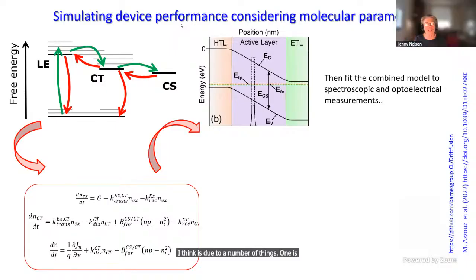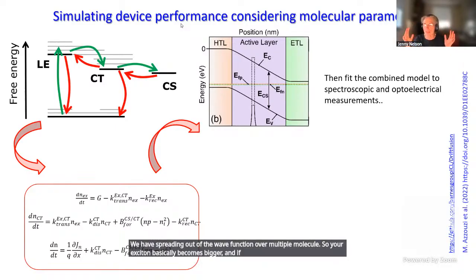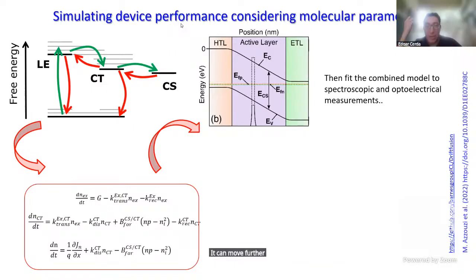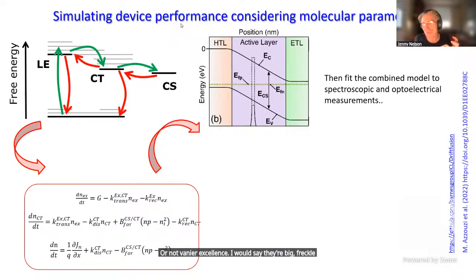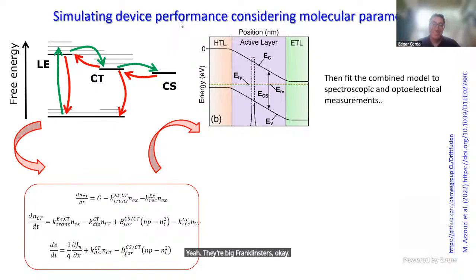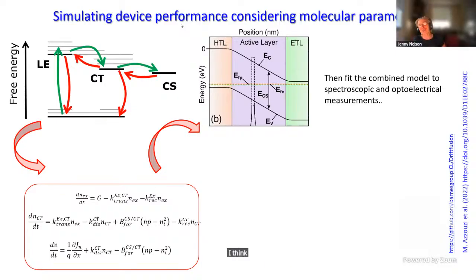One is that with these molecules that are very flat and can be packed together in an ordered manner, we have spreading out of the wave function over multiple molecules. So your exciton basically becomes bigger, and if it becomes bigger, it can move further. Yeah. But are these Frenkel excitons or Mott-Wannier excitons? I would say they're big Frenkel excitons. Okay. I can't call them Mott-Wannier excitons unless I've got a band structure, and I don't think I do.